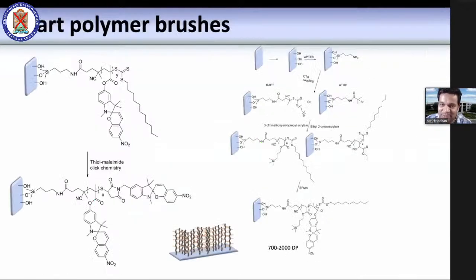So here we use the smart surfaces. You can use smart surfaces, say two-dimensional, using glass or silicon, any substrate, and grow polymer brushes of an azobenzene-based molecule or spiropyran-based molecules, which are light responsive. So here you have a side chain of spiropyran, and you can use this like azobenzene. And here we use a kind of radical polymerization technique.